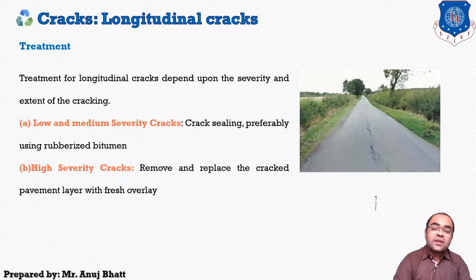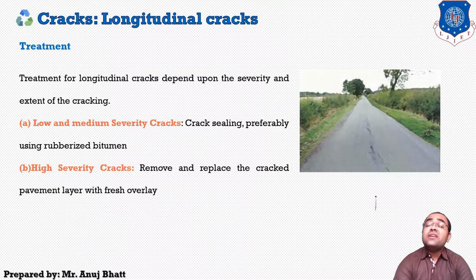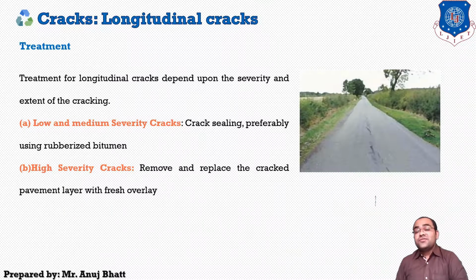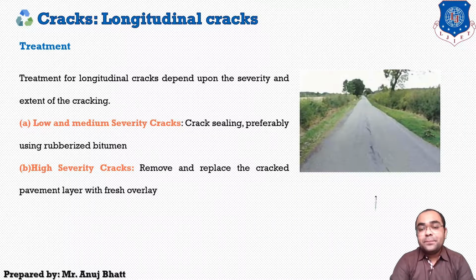Low and medium severity cracks can be treated with crack sealing, preferably using rubberized bitumen, and if there are high severity cracks, we have to remove the old construction or old pavement, and we have to replace the cracked pavement layer with the fresh overlay.